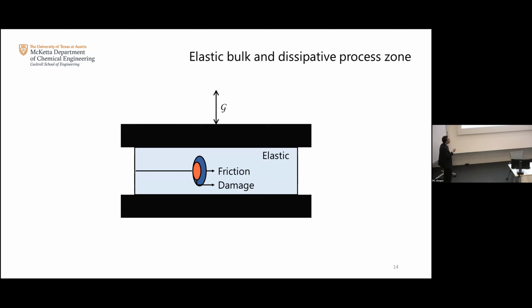We had a system which is elastic in the bulk, so very far away from the crack tip. If I apply very low deformations, the system is behaving like this, perfectly elastic, and very close to the crack tip, I'm going to have an interplay between friction and damage, and I'm going to try to image what this damage is going to be in order to get a measurement of how much energy is dissipating during fatigue fracture.